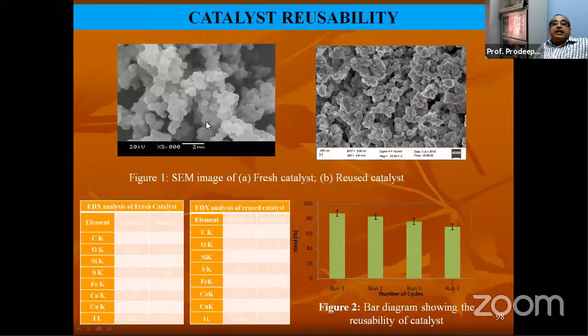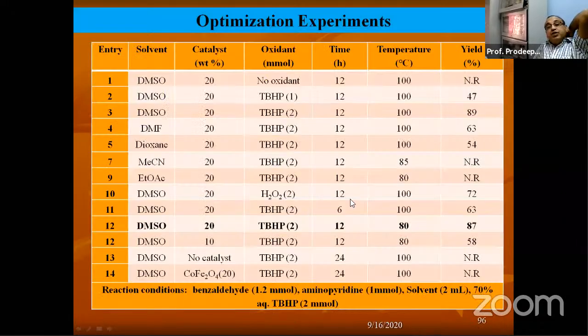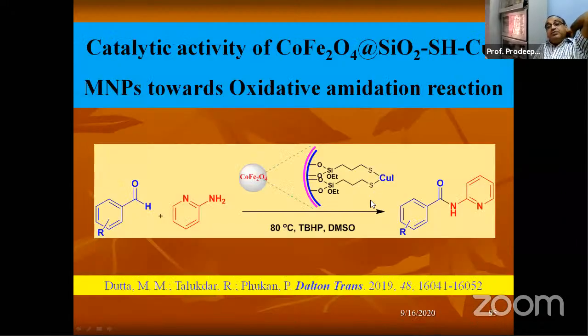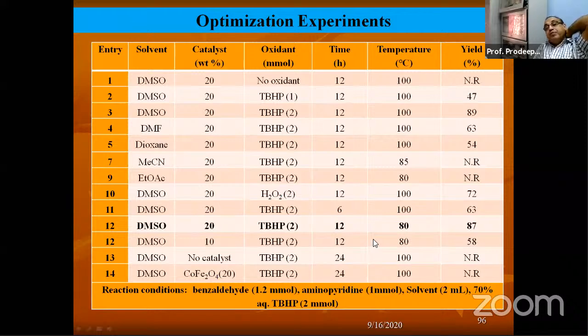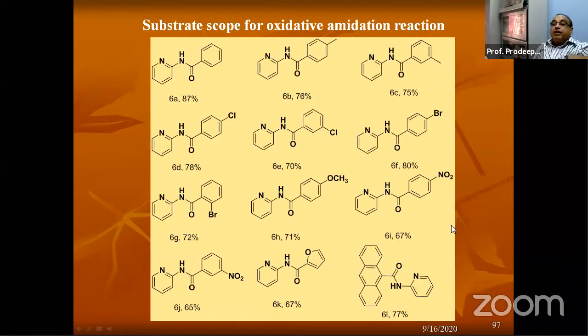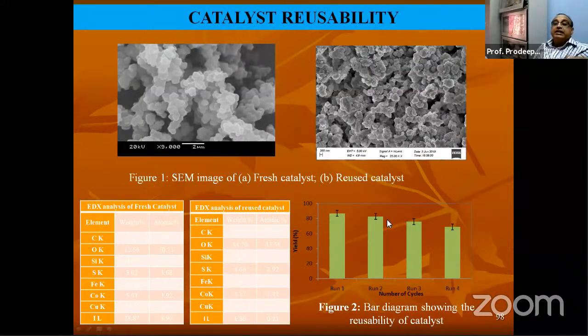And these are the catalytic characterization. So this is a SEM image. You can see very nice structures. However, in this case, we observed some problem. Since cuproside was hooked on the surface, and we have used TBHP as the oxidant, we found that slowly its catalytic activity declines when we go for repetitive use of the particle.